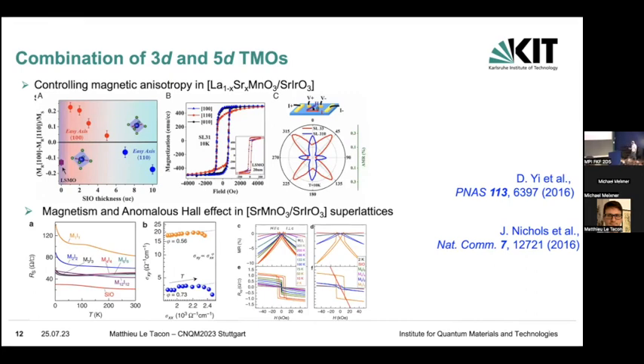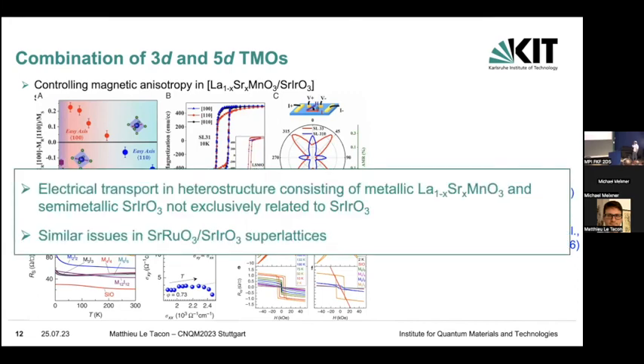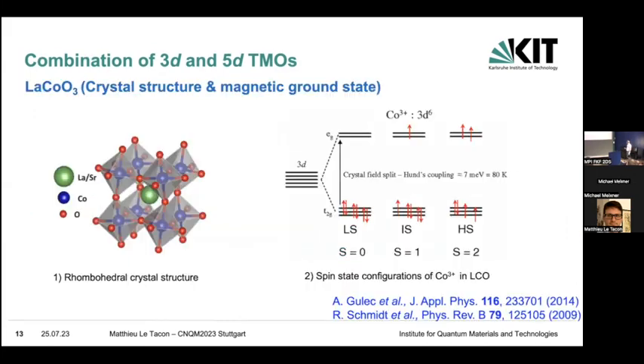And that's actually the issue: when you do electrical transport in this kind of materials, you have the transport coming from the iridium, but also from the metallic manganites. And so it's a bit hard to disentangle what is coming from the iridium and what is coming from the other layer. You get similar issues, with a very interesting result on strontium ruthenates, but the same thing when you do transport, because the strontium ruthenate is also metallic, it's a bit hard to know what is really coming from the iridium.